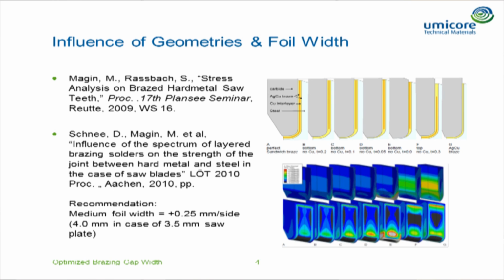And there you can see here the optimum, when you have a very continuous copper layer in between the cemented carbide and the steel. Then you can see different failures, and in the last one you can see the brazing alloy without any copper layer in between. On the bottom side you see what happens on the cemented carbide tip, especially on the surface, and you can see the influence of the sandwich brazing alloy directly when you compare it with a normal brazing alloy. There you can see the tensile stresses on the top surface of the cemented carbide, and here you can compare it with the sandwich brazing alloy, and there you can see how it works.